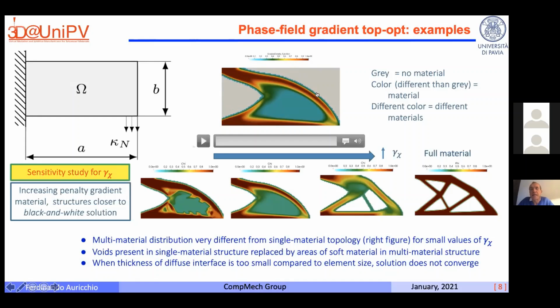The other colors, except gray, instead mean different materials. So basically you can see that in the red area and in this part here, you have different materials. So the structure that we obtain through these topology optimization schemes is already a structure with a gradient, which you can easily produce with additive manufacturing. The very nice thing is that you can clearly change the parameters in your model. And depending, for example, on this parameter gamma chi, you can obtain different structures.